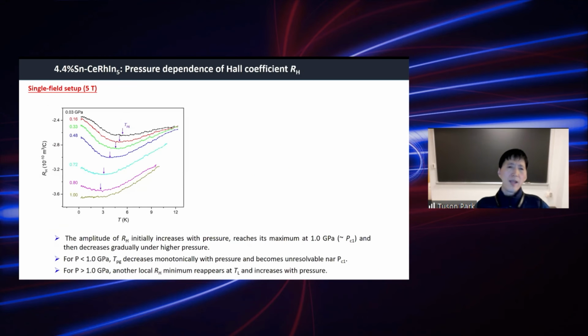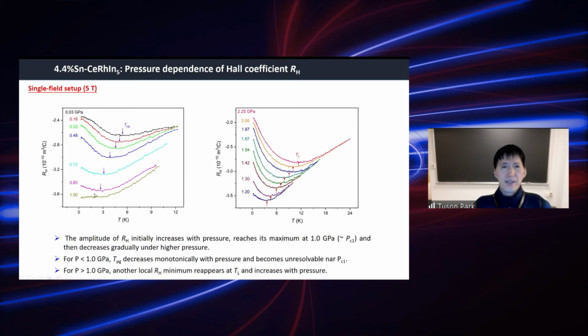So here we show the low temperature Hall coefficient for several pressures. With increasing pressure, the pseudogap temperature decreases and the signature becomes weaker, and around 1 GPa it is gone. And at the higher pressure region, we can see that the local minimum occurs again. But we think that this is not due to the pseudogap, so we call it just T sub L, indicating something